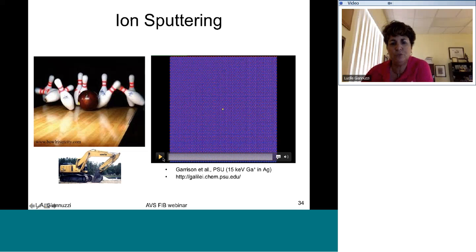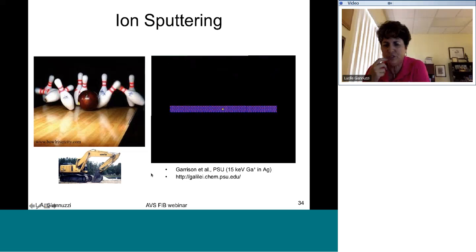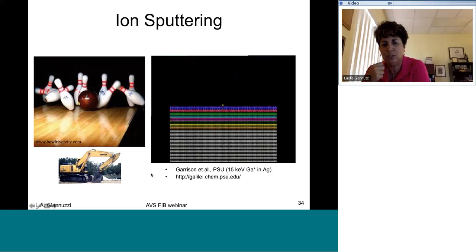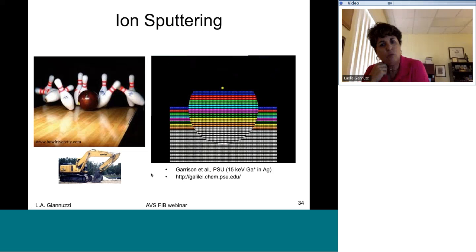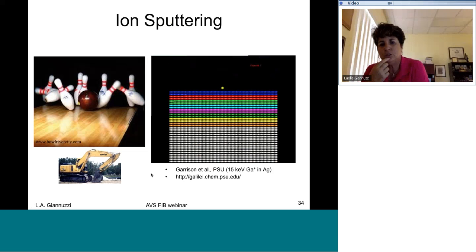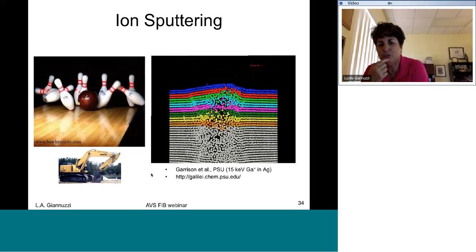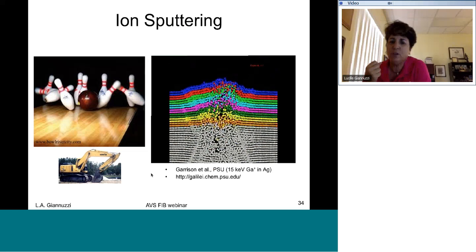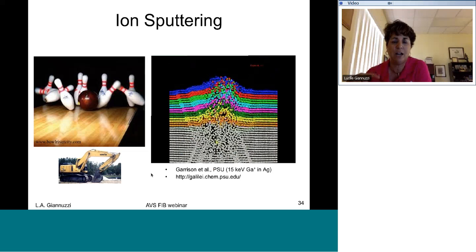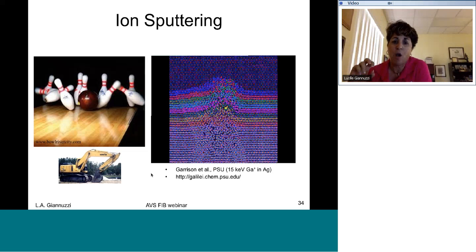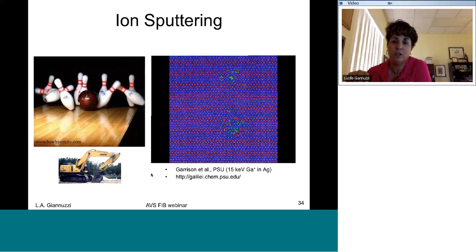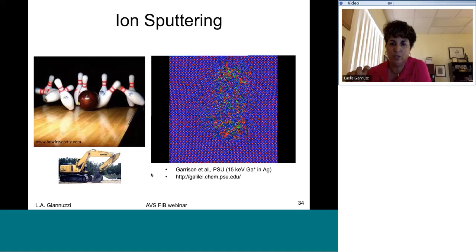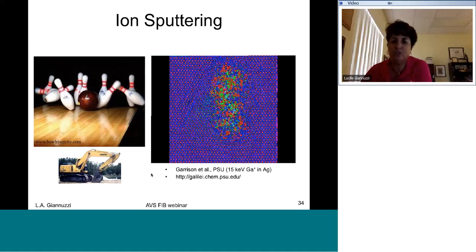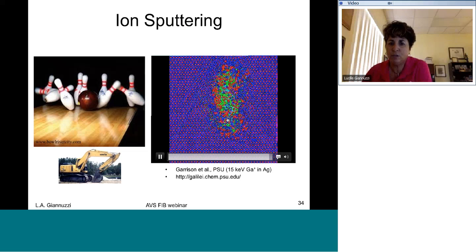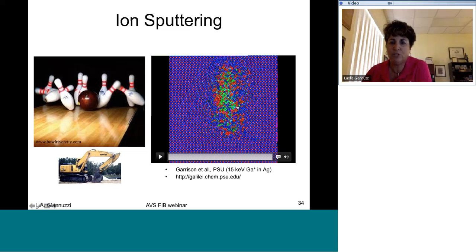So let me show you a movie. This is from Barbara Garrison at Penn State. This is 15 keV gallium in silver. You can go to our website and see a whole bunch of these different movies. So there's the side view. The one thing you note is that this is just one single ion, and you can see hundreds, literally hundreds of recoils that are generated. This is the top view. So it's coming in at an angle, so you can see that everything is sort of coming in about here, so everything is pushed this way.